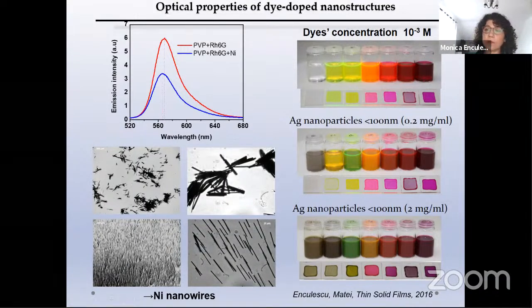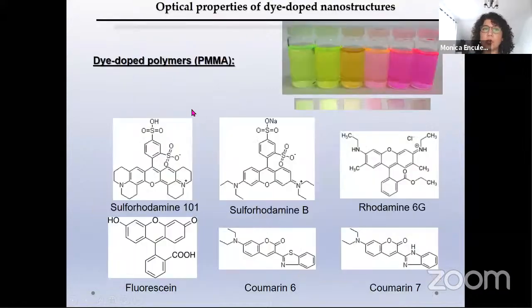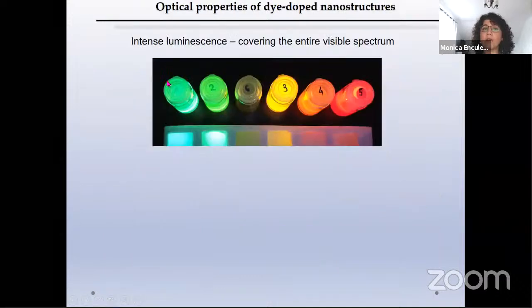And even with the morphology of this type of co-doping particles, wires, the emitting properties can be changed. So we have dye-doped polymers. In this case, it's only about polymethyl methacrylate, that can be doped with different dyes. So we have dyes that cover the entire visible spectrum, from the red ones that are rhodamines, to the green ones that are coumarins, very close to the blue part of the visible domain. So we have intense luminescence that covers the entire visible spectrum.